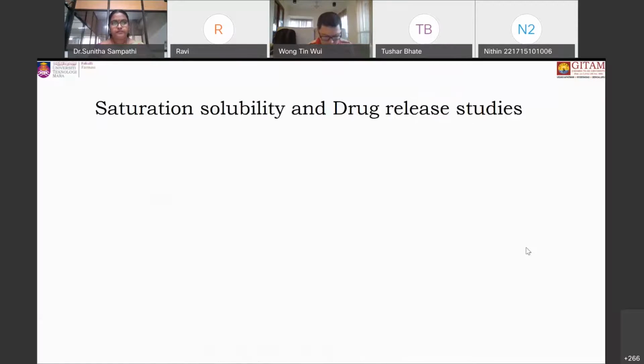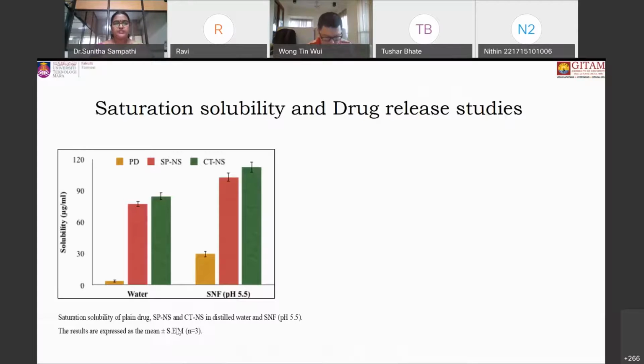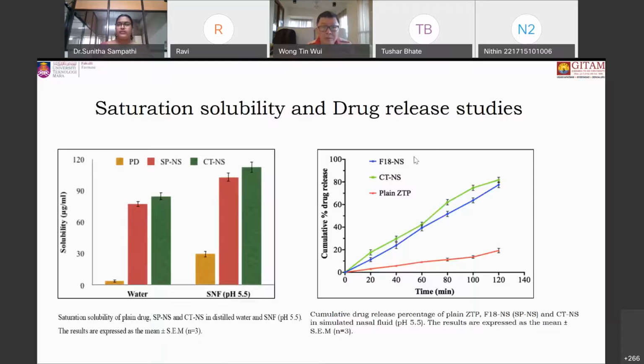And the particle size here was reduced to 130 to 140 nanometers, and they are spherical and discrete and not agglomerating. Now later we subjected that to saturation solubility studies, and we found that the nanosuspensions prepared with the two techniques, sonoprecipitation and the combination technique, have high solubility of the drug as compared to the plain drug. In a similar direction, we then continued with the drug release studies, which we did in simulated nasal fluid of pH 5.5. So if you look at the graph, the plain drug is releasing less than 15% at 120 minutes. Whereas the nanosuspension prepared with the combination technique was releasing nearly 80% of the drug in 120 minutes, which can be attributed to the reduction in the particle size as explained by the Noyes-Whitney equation.